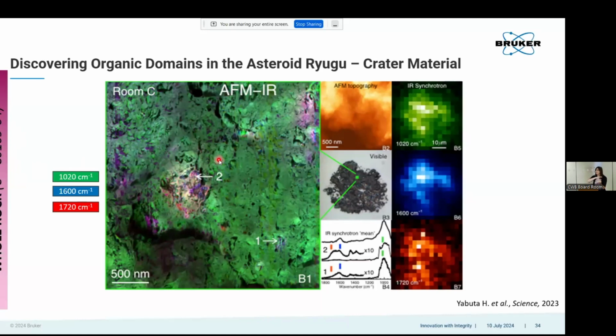In this case, they're using a diamond knife to cut through them at a defined thickness, which for a meteorite or an asteroid is extremely hard to do because they can be very fragile in some locations. You can have very hard areas and very soft areas such that it can be hard to cut through. Like imagine cutting through a bagel with raisins in it. You very rarely actually cut through a raisin. You more likely bend around that raisin and get it on one side or the other. So you really want to cut it in such a way that you're capturing all that material throughout it.